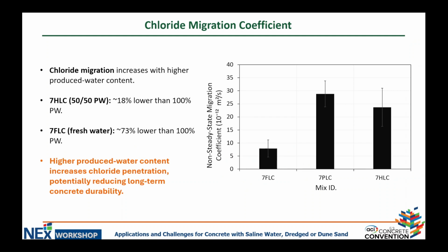Here we can see the chloride migration coefficient, the NT BUILD 492, which is the non-steady state chloride migration coefficient. So we measured it for only 3 mixes. We are still doing testing. As we can see, as we are increasing the content of produced water, there is a higher coefficient